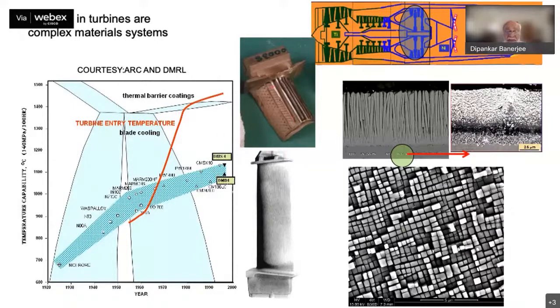And we've learned to overcome this by internal cooling of these blades and vanes, so that the blades are hollow and have these complex channels into which cooling air is driven, taken away from the compressor of the engine. And finally, you also coat these blades with insulating thermal barrier coatings, usually zirconia or a form of zirconia, together with an oxidation-resistant coating that lies between the substrate and the thermal barrier coating. So this is a complex material system which allows the operation of these materials well beyond their melting point.